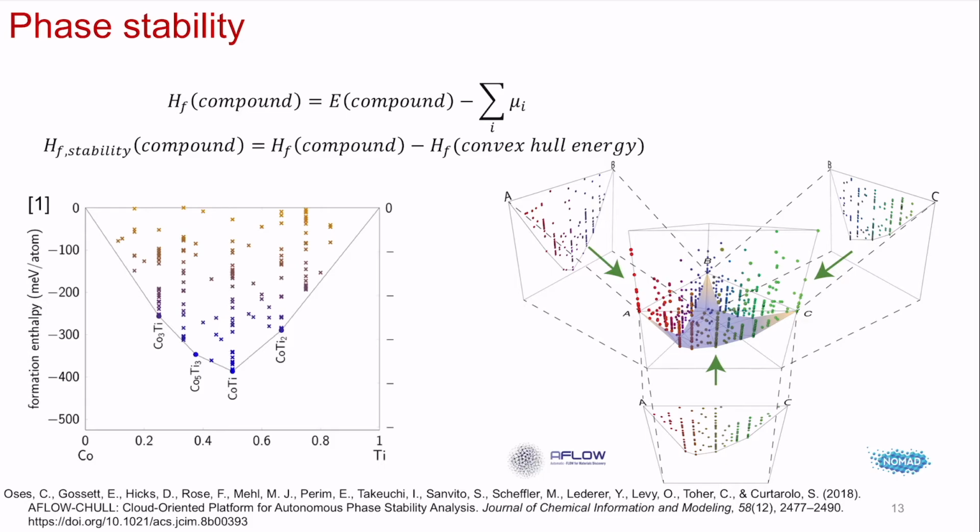So there are atomic origins to all of this, and they're all intermixed with each other. So from density functional theory, we can predict, okay, if we have two species for a simple case, or even a more complex ternary phase diagram, we can map out the species that are most likely going to form when we put two elements together, or three elements together, or pseudo-binary. You have two binary end members. What does that form? So we can make what's called a convex hull.